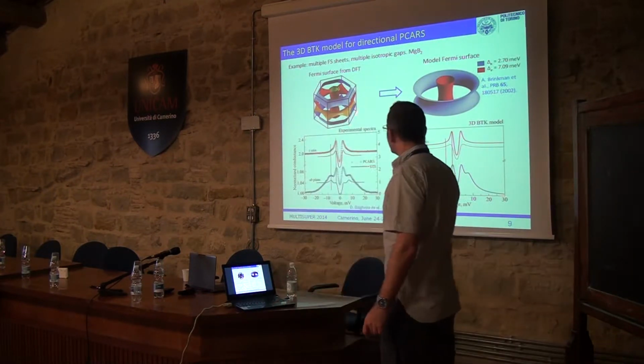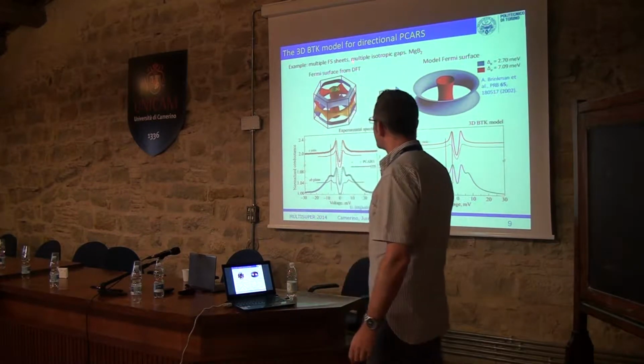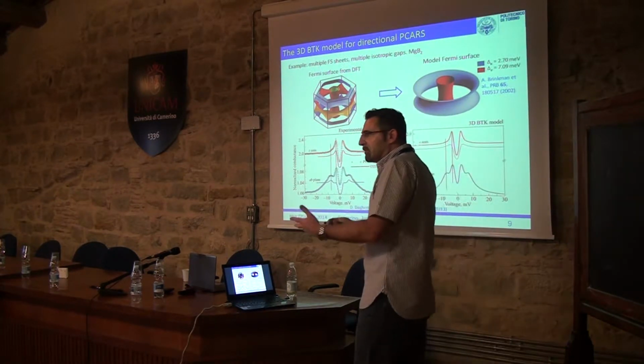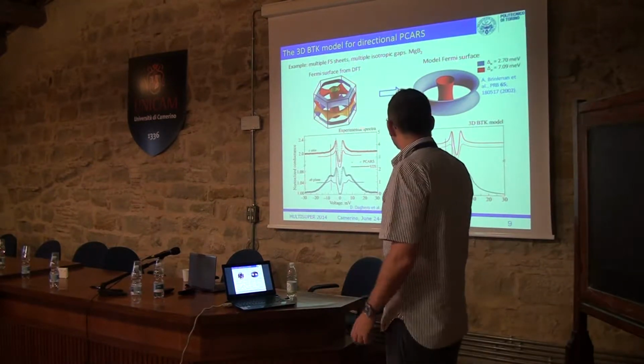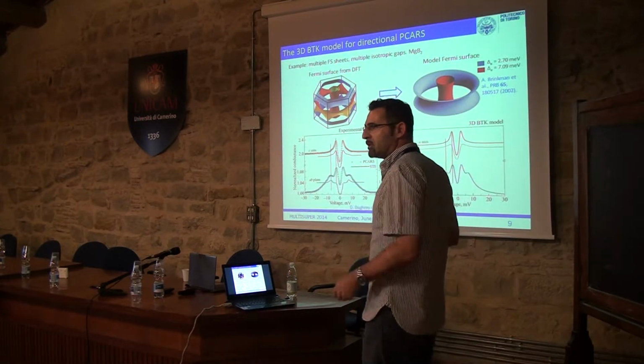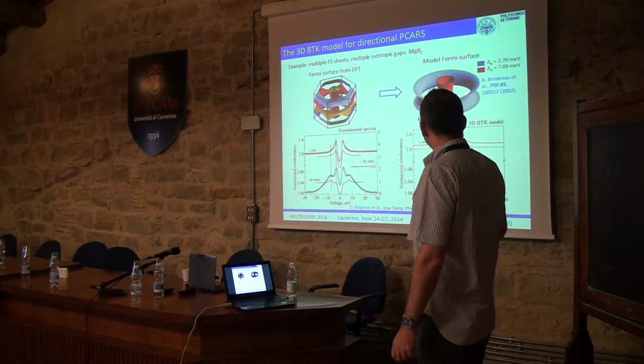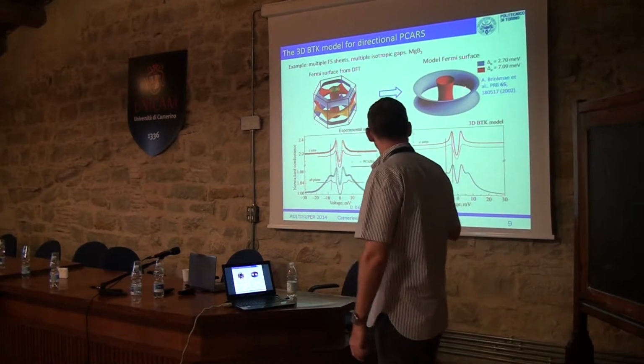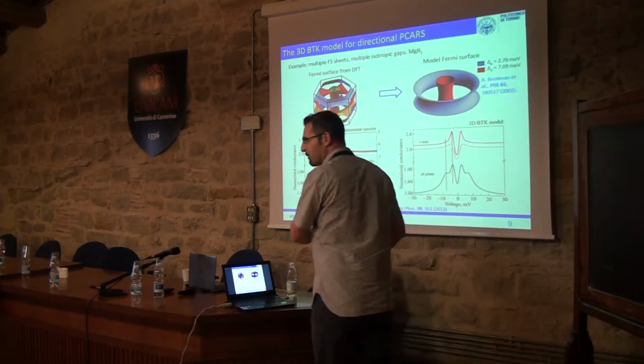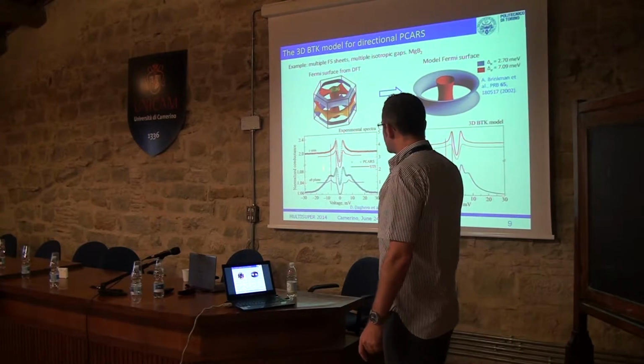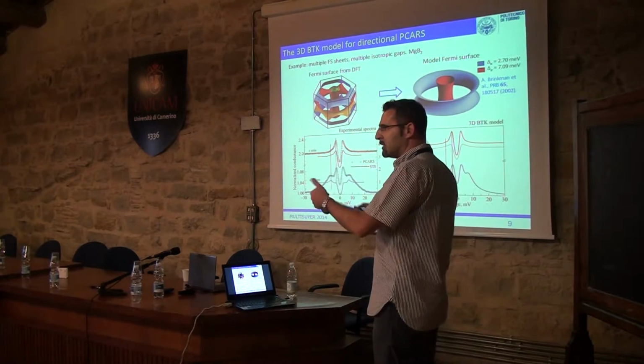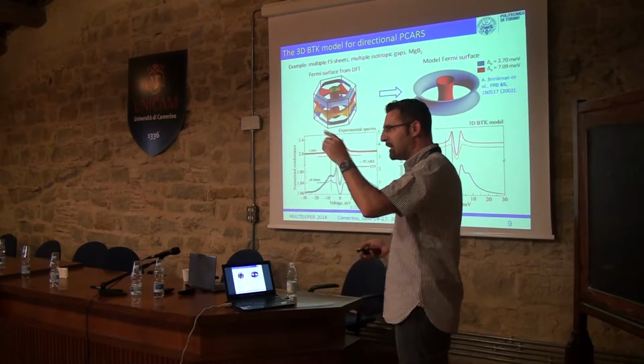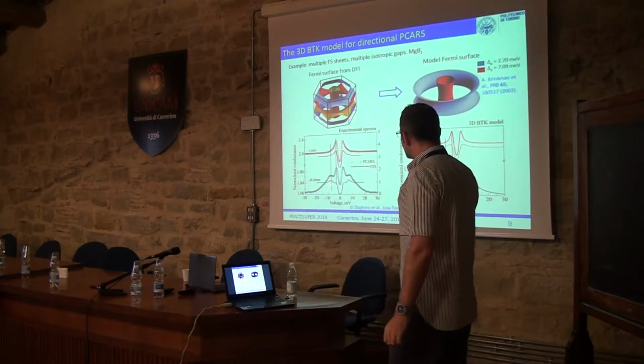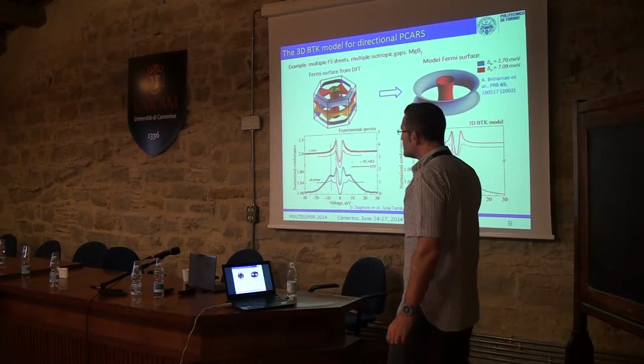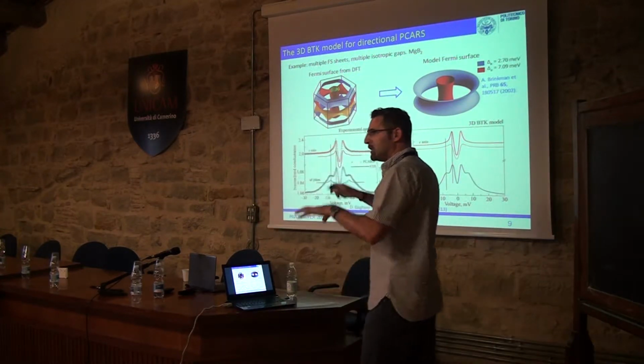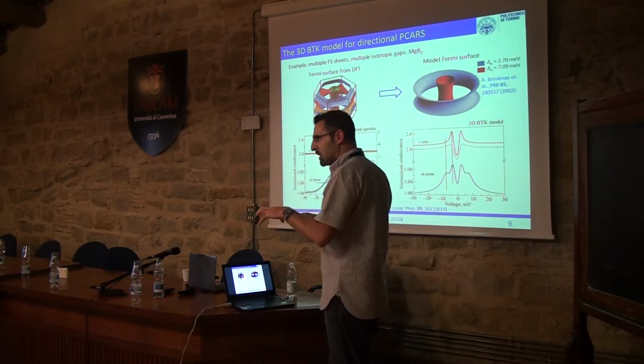An example is the application to MgB2. It really works, because this is the Fermi surface from DFT calculations. Just to have easier calculations, we use a model Fermi surface that keeps the most prominent features of the original one. And then if we associate to the pi band the pi gap from first principles and to the sigma band the sigma gap from first principles, we can obtain spectra that perfectly fit the experimental ones. Of course, here we have additional parameters, that means Z, which is the parameter that controls the height of the potential barrier between the normal metal and the superconductor. But actually, the shape of the curves is perfectly well reproduced. Note that in the 3D BTK model, the weight of the different bands is not a parameter, because it is given by the shape of the Fermi surface.